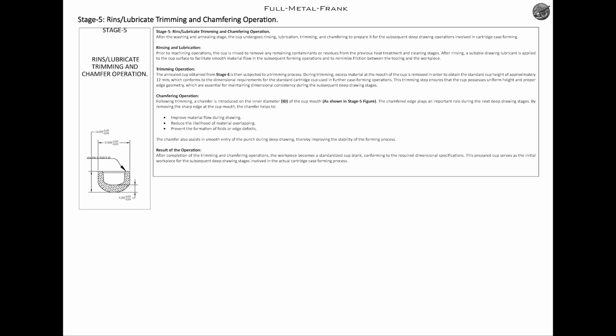Chamfering operation. Following trimming, a chamfer is introduced on the inner diameter, ID, of the cup mouth, as shown in the stage 5 figure. The chamfered edge plays an important role during the next deep drawing stages. By removing the sharp edge at the cup mouth, the chamfer helps to improve material flow during drawing, reduce the likelihood of material overlapping, and prevent the formation of folds or edge defects. The chamfer also assists in smooth entry of the punch during deep drawing, thereby improving the stability of the forming process.